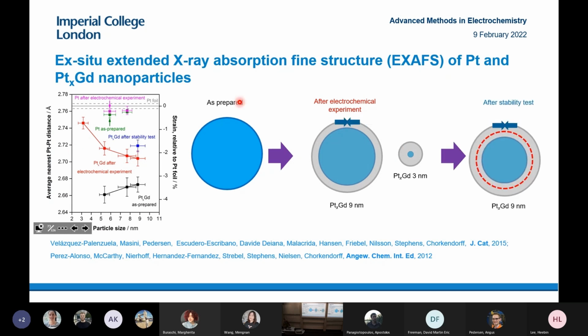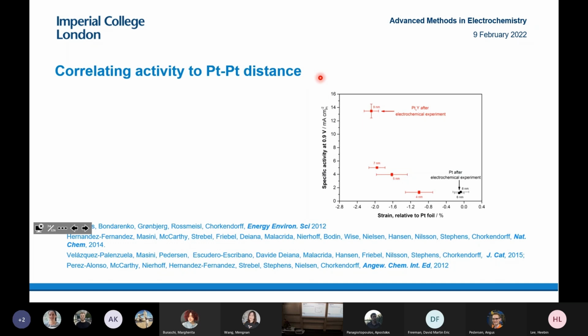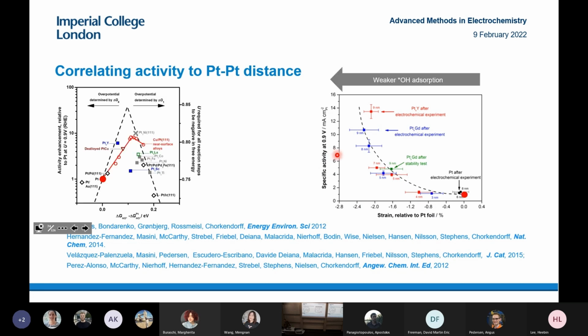Another thing we found is that we saw lower activity after stability tests, and this is also consistent with further leaching of the rare earth. We think we have a thicker overlayer. So we can correlate specific activity relative to strain, for pure platinum, platinum yttrium, and platinum gadolinium, and we see a really nice correlation. I think even when we're putting one after a stability test, we're moving up and down the strong binding side of the volcano.